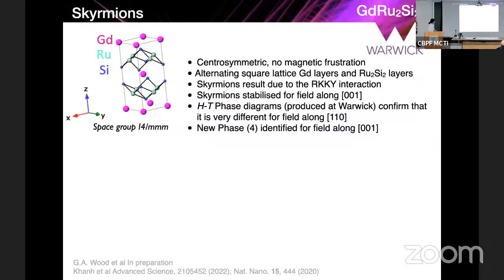And the very last one that I'd like to talk to you about is the gadolinium ruthenium 2 silicon 2. Now this again is a centrosymmetric structure where there is no magnetic frustration either. So it doesn't have the Dzyaloshinskii-Moriya interaction, nor does it suffer from magnetic frustration, okay? So once again here, it's not very clear what the mechanism is for the formation of the skyrmions that are proposed to exist in this. What is thought is that the skyrmions result due to the RKKY interaction in these.